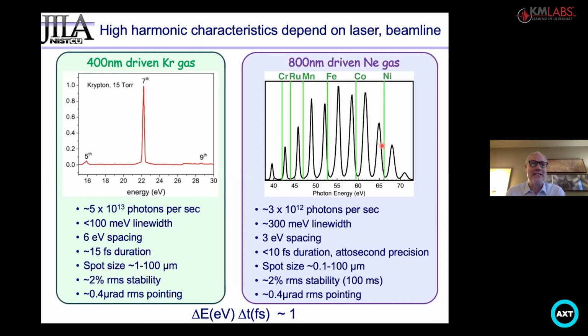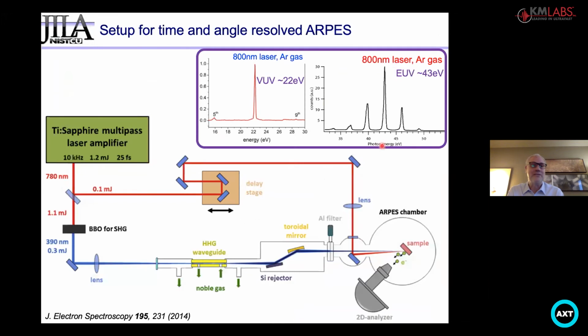And in this case, there's one harmonic: the 7th harmonic of 400 nanometers is at 22 eV, and that's a great photon energy for ARPES. So there's flexibility in how you can do this. You can also rotate the polarization of the laser to rotate the polarization of the light source. This is a typical setup.